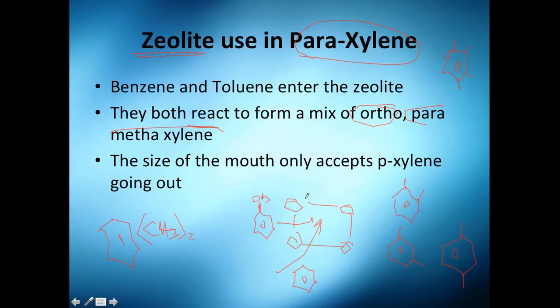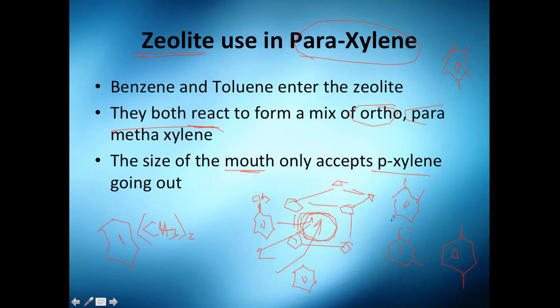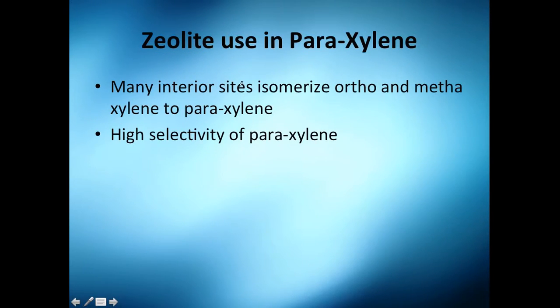What's going to happen is that because the zeolite pore size is small, only the para-xylene can exit — because of its linear shape. The ortho isomer is too wide, and the meta isomer is also too bulky. So they react inside, and even though all isomers form in the interior, those that cannot exit will isomerize.